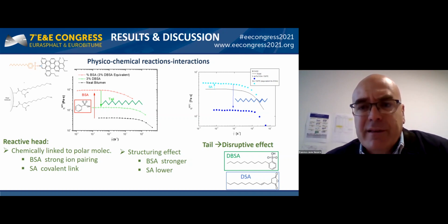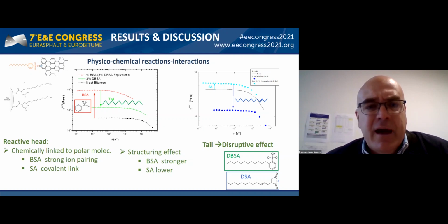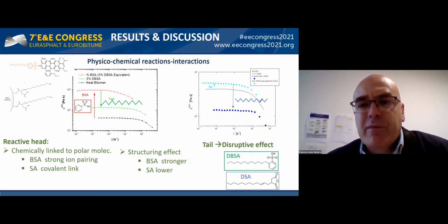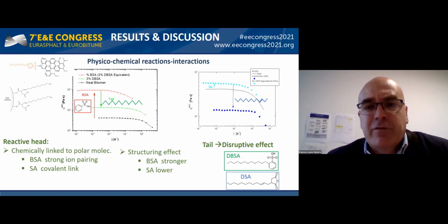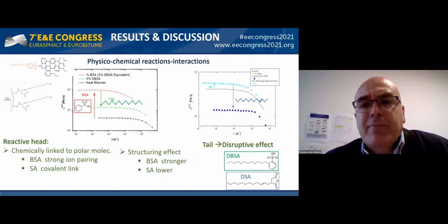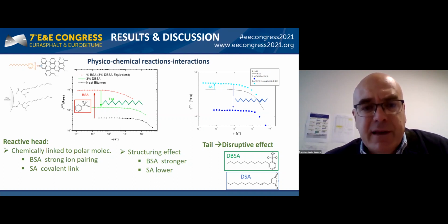Evidently, this outcome should be related to the reactive head of the surfactants and to the type of physicochemical interaction with bitumen molecules. In order to shed some light on this issue, these molecules are also being modified with DBSA and the sodium salt DBSS, with the same molar amount of the polar head of both surfactants. It is clear from the figure on the left that the sodium salt hardly modifies the rheological response, whereas benzene sulfonic acid brings about a huge increase in viscosity. Therefore, the reported formation of ionic pair has a strong structuring capacity.